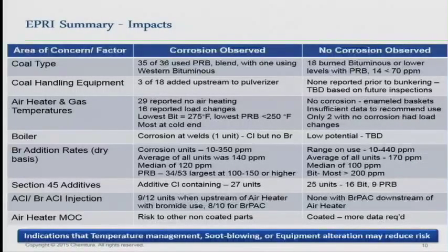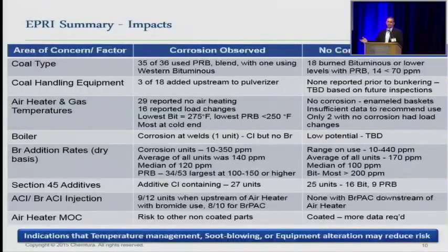Activated carbon or brominated activated carbon injection, they've looked at that now too. They showed more of an issue injecting upstream of the air heater, which somewhat makes sense when you're injecting a solid there, where you have the potential for those solids to settle out on a surface somewhere. Then if you have condensation of acids, or something else like that going on, where you're not doing as much soot blowing, now you have a surface that can hold that acid right up against that metal, and that's where you're going to start seeing the big corrosion issue.